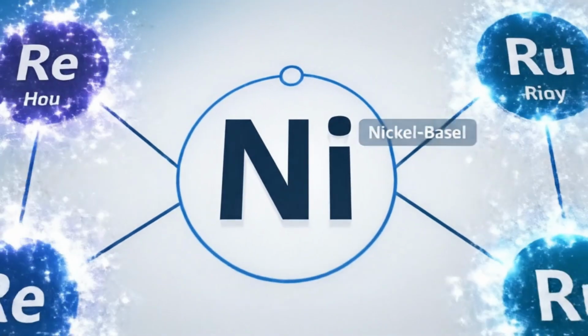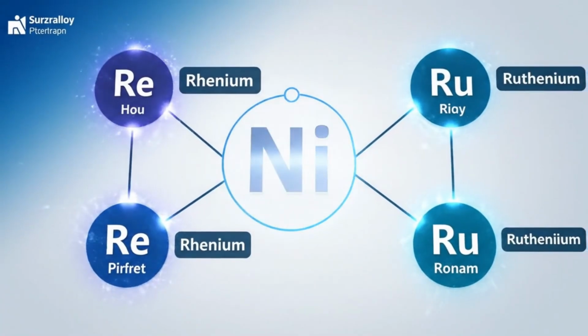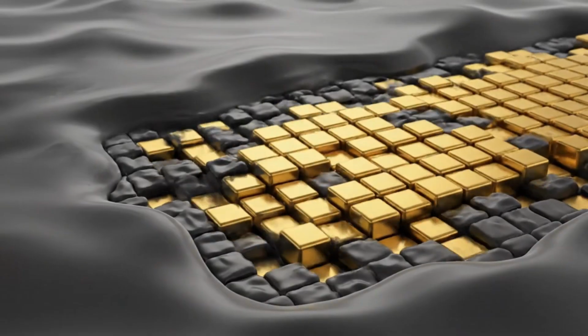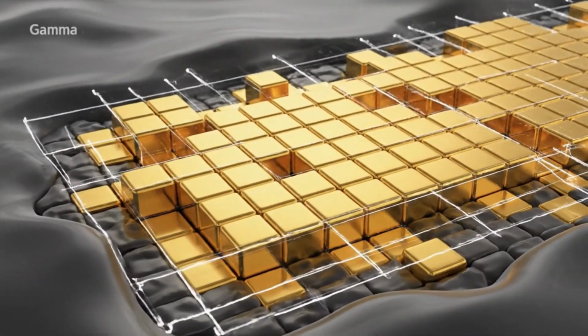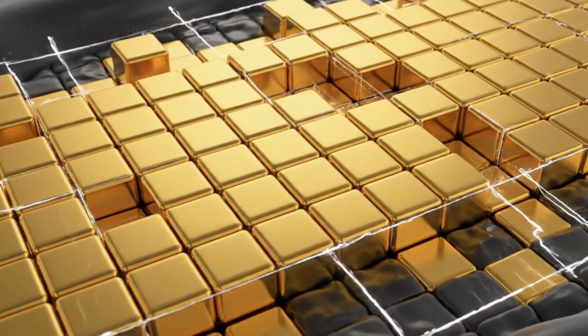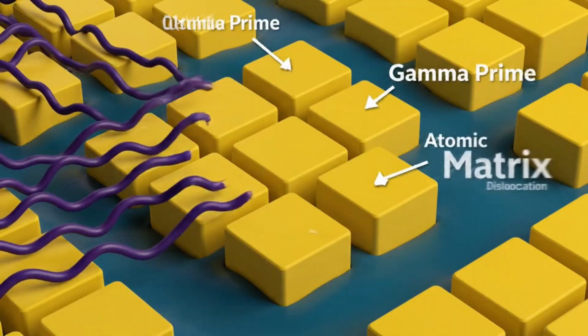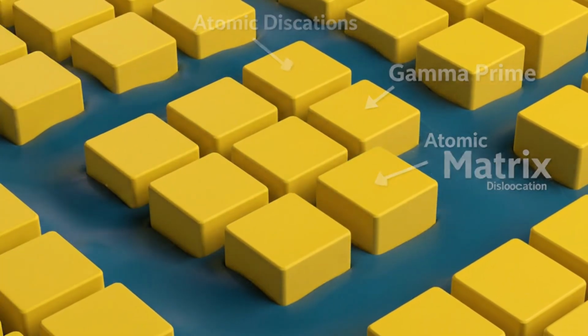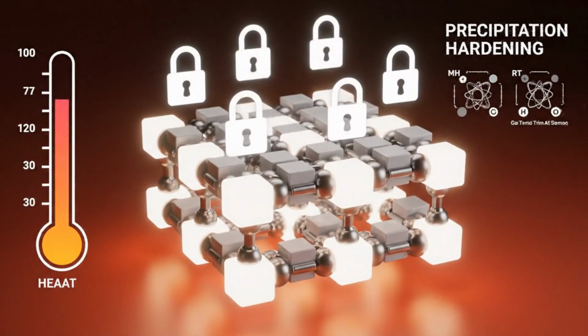But the chemistry is just as important as the structure. We call these materials superalloys for a reason. When this single crystal solidifies, it forms a specific microstructure known as the gamma-gamma prime structure. Imagine a brick wall. The bricks are hard, cuboidal particles called gamma prime. The mortar holding them together is a softer matrix called gamma. When the material gets hot, unlike most metals that get softer, this structure actually maintains its incredible stiffness.